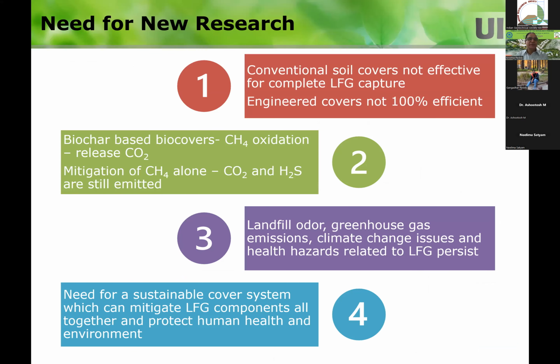Then we said, okay, this looks very promising. Let's do a lot of additional research to see if we can make a cover that could be applied in the field. So we know that just using soil covers, conventional covers, even with engineered landfill gas capture, they're not going to be effective. So we're going to have some fugitive gas emissions. And based on the preliminary testing, we found out that biochar-based biocovers can oxidize the methane into CO2. But that is solving the problem only partially. If you convert CH4 into CO2, that CO2 is still a bad thing. And then you have a lot of CO2 that is emitted that we are not considering.